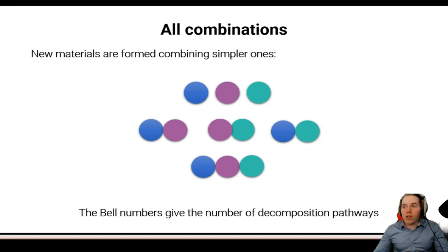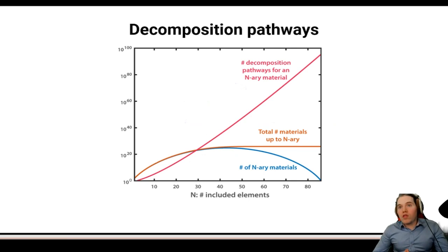All right, so you can actually count the ways that these materials might fall apart, and these are the Bell numbers. And these are plotted here on the red curve. So you see that these Bell numbers actually skyrocket even faster than the actual number of materials you might be able to create. And if you look at the one material we can form with all 86 elements, if we pretend they all have the same geometry, then there are 10 to the 100th ways that this one material might fall apart. And thus we can imagine that this is pretty much impossible. So somewhere along this line, there will be a limit at which point it will become very rare to impossible that we can create a material that is so complex, just because it has so many ways of falling apart. Now, where this limit is actually not yet known.